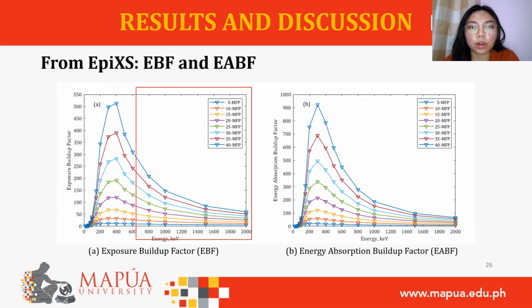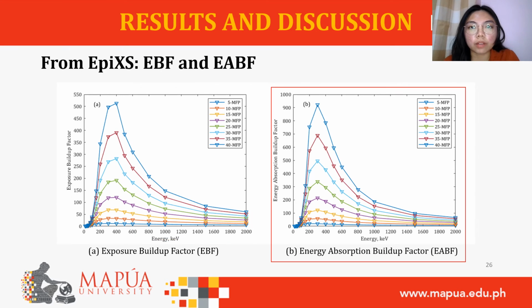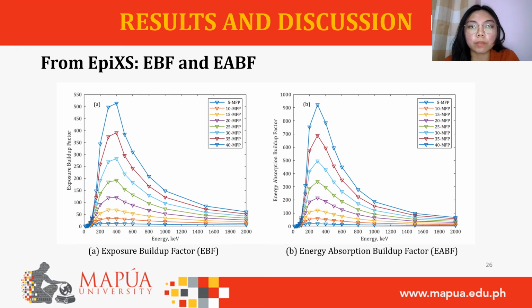The behavior of the EABF response at varying MFPs is also almost similar to the EBF response as the photon energy increases. Moreover, an increase in the MFP causes an increase in the EABF and EBF values because the latter is in direct proportion with the scattering volume. In this case, the photon scattering interactions will be more likely to occur, increasing the EABF and EBF values.